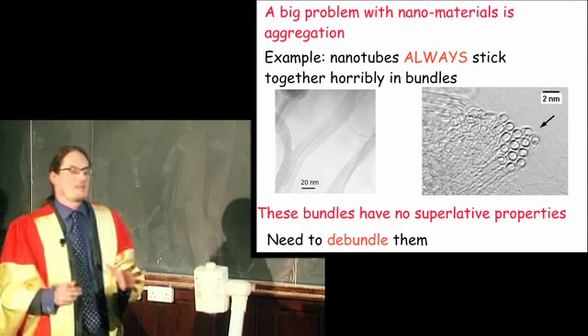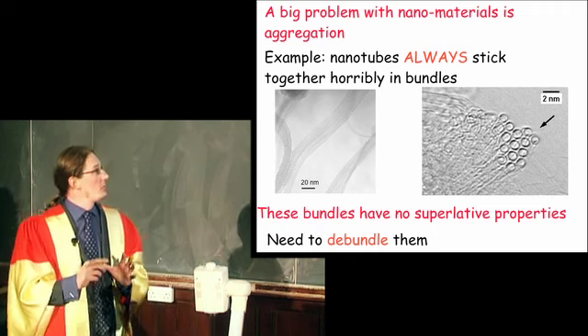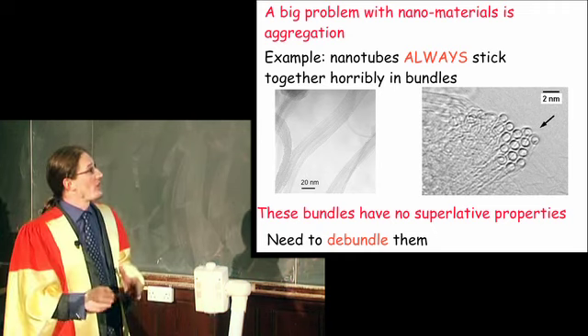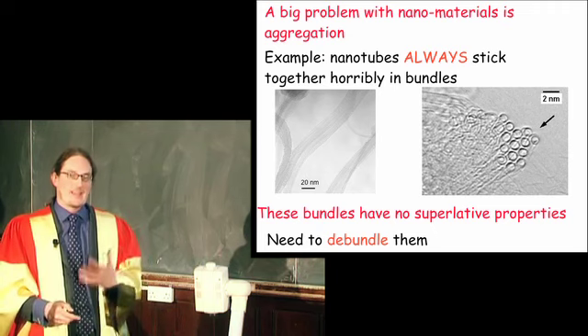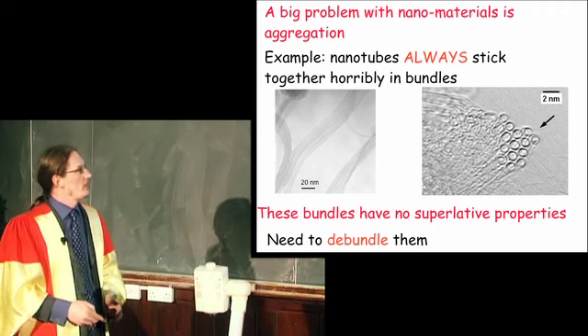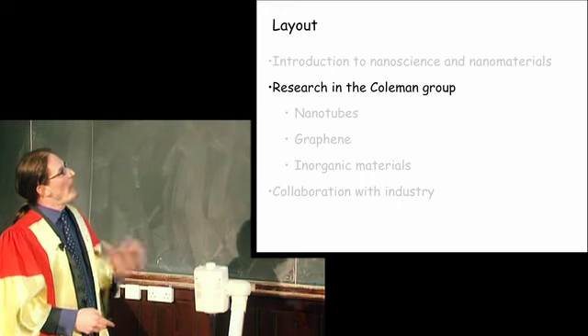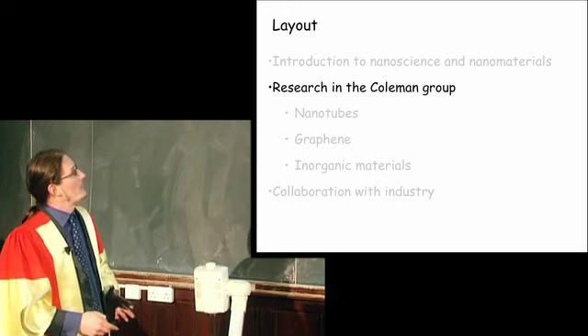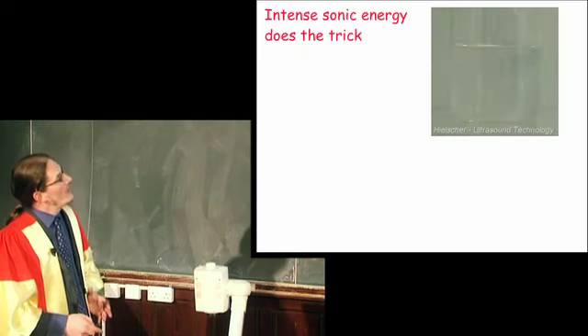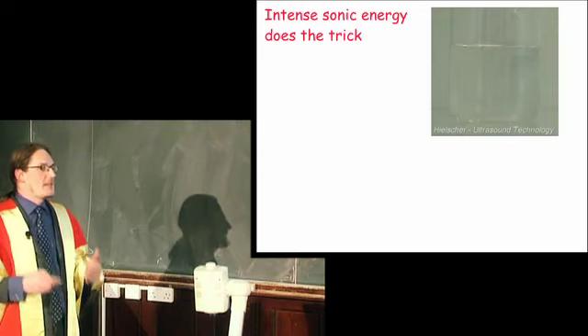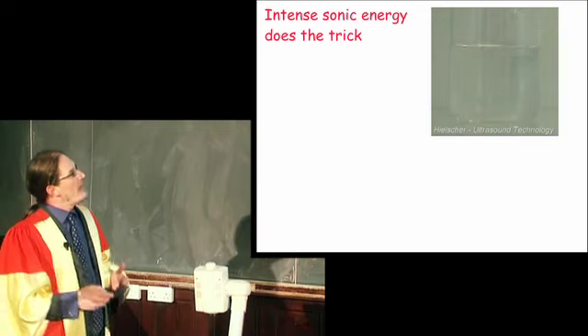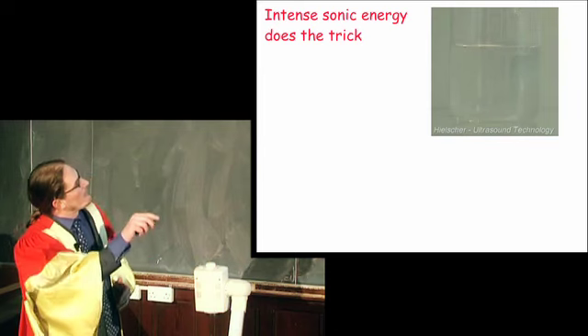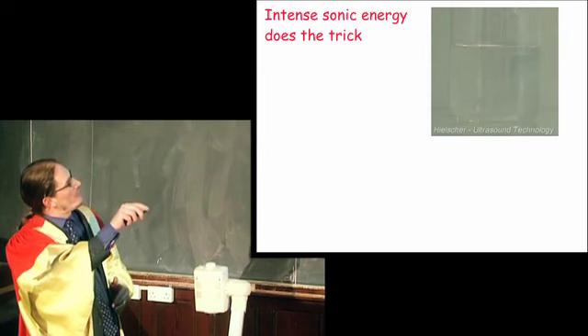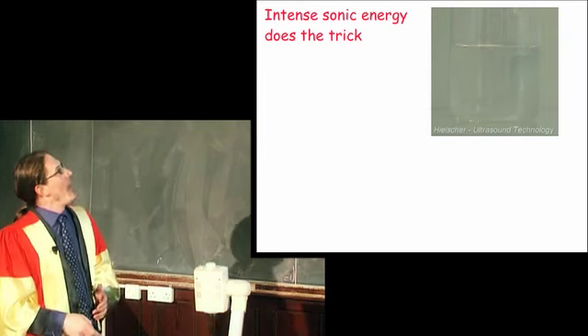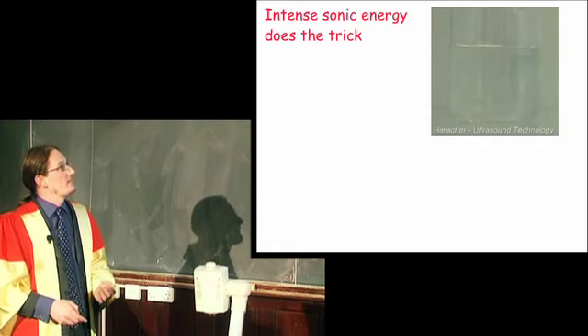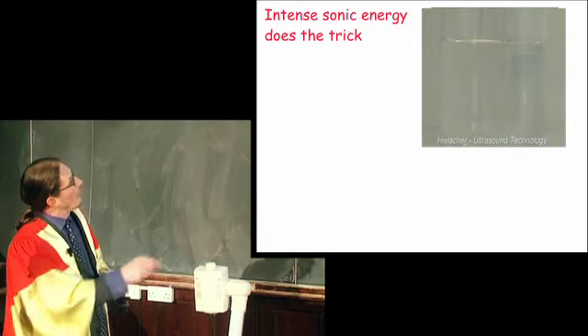So for about 10 or 15 years, people have been doing a lot of research to learn how to debundle them, to get individual nanotubes from these aggregates. And this is where my research comes in, because that's effectively what I do. So simply speaking, the easiest way to do this is to take nanotubes. You can't see them, but a small quantity of nanotubes have been put in a beaker of water, and then you add intense sonic energy. So this is an ultrasonic probe.